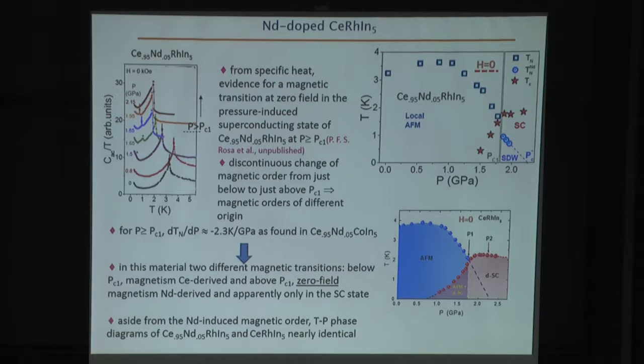And the results of these data in zero magnetic field are summarized in this temperature pressure phase diagram, where we see that the Néel boundary decreases. There is a line of strongly pressure-dependent phase transitions that develops below the superconducting transition temperature. And these features in specific heat move rapidly to lower temperatures with increasing pressure.